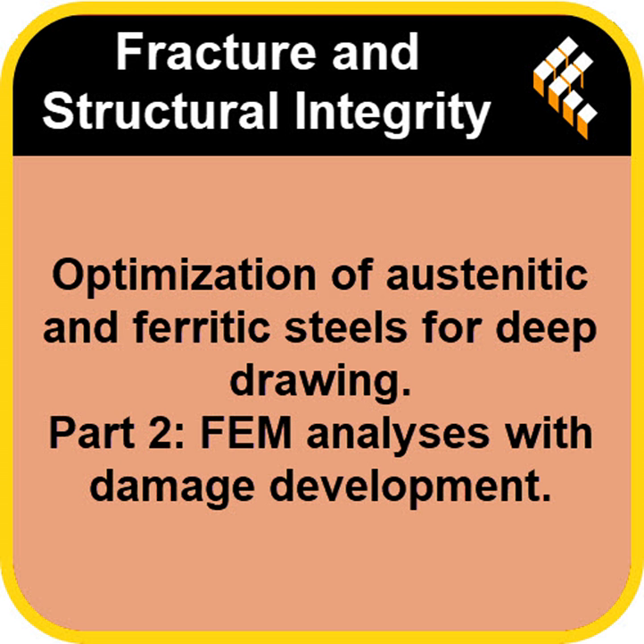Okay, capturing the real-world failure. Then they simulated that exact same tensile test in the FEM software. They tweaked the advanced material model parameters within the simulation until the FEM prediction perfectly matched the force, the deformation, and the point of fracture they saw in the real test. Ah, so they used the physical test data to teach the simulation how the material really behaves at the point of failure. Exactly. They were essentially reconstructing the missing part of the true stress-strain curve computationally, guided by the physical experiment.